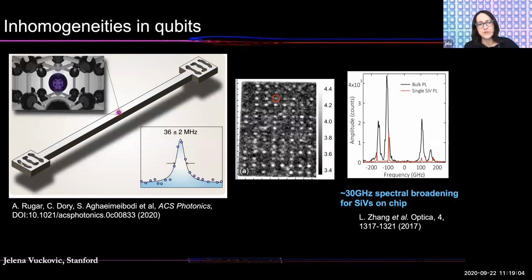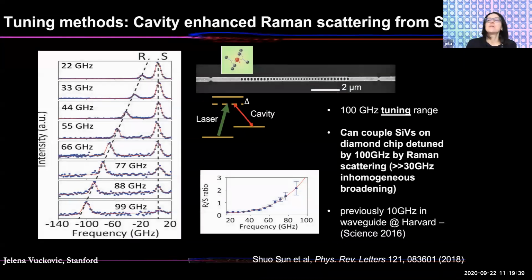I said that these are inversion symmetric color centers that are immune to the environment, but any strain in the sample would actually leave that, and it would not be immune to the environment anymore. So this is primarily a result of strain in the sample and then some other resulting impurities. So we have about 30 gigahertz of spectral broadening for silicon vacancies. Again, this depends on the color center and the materials that we're using and the purity of the materials, but there is about 30 gigahertz of broadening that you have to deal with. So in order to deal with that and to address that, we've developed a variety of methods for tuning.